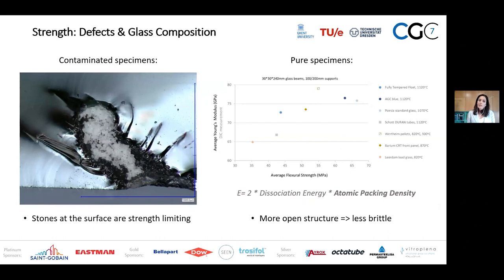So we saw that, for example, for the less pure series, the defects that we would get from the contamination were really the strength-limiting flaw. While in the more pure specimens, the glass composition was really starting to play. And then we would see a range of properties, and more importantly, we would see that, for example, the highest Young modulus would not necessarily mean the highest flexural strength.